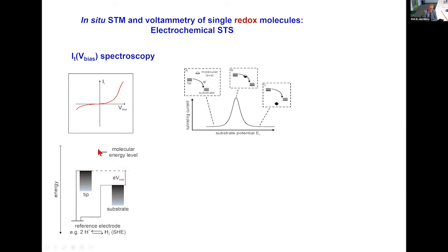The molecular level will also be lowered, but not as fast as the substrate Fermi level. But sooner or later, it will cross the Fermi level of the tip potential, and then a new mechanism will appear. But for the bias voltage, we have to go to very high bias voltages before we will see this other effect. This is something unique for electrochemical scanning tunneling microscopy. We can either change the bias voltage at fixed potential of one of the electrodes, or we can fix the bias voltage and change the two potentials in parallel.